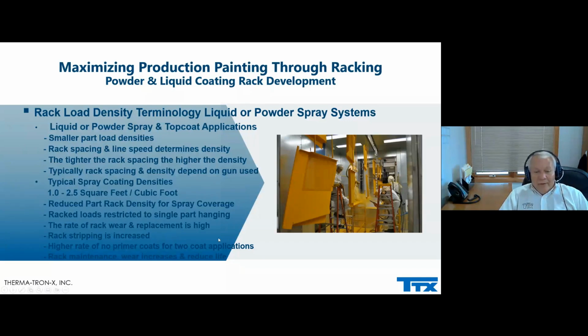The rate of rack wear and replacement is higher than electrocoating, just so you're aware. Electrocoating is great if you have up to 50% one color on a paint line. If you're doing 100% of one color, a single coat like red, black, green, whatever it may be, that's the most efficient, and you want high film builds. Some of the high-film electrocoat, you can get up to almost 1.5 to 2 mils now.